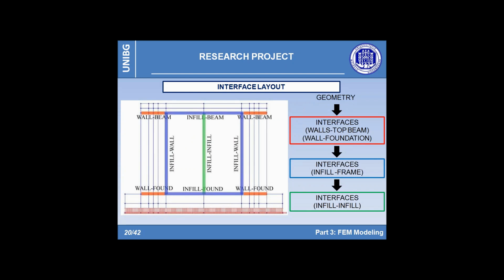These tools try to take into account the dowel action guaranteed by the longitudinal bars in correspondence of the construction joints. In this way, the sliding observed during the test can be modeled elastically on the basis of experimental measurements by means of an equivalent stiffness. This device also permits to reproduce numerically the correct value of the elastic stiffness registered for Wall 1. On the contrary, neglecting this sliding phenomenon, the finite element model tends always to overestimate the stiffness of the structure.